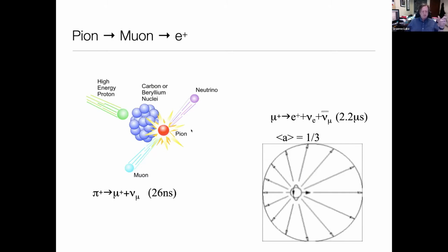We first of all, of course, have to do muSR. You need to have muons. So we make these at a particle accelerator, and we typically use TRIUMF in Vancouver. You start off with a 500 MeV proton beam, which hits a low Z target like carbon or beryllium. And one of the things you make in that reaction are pions. You make a lot of other things, but some of the things you make are pions.